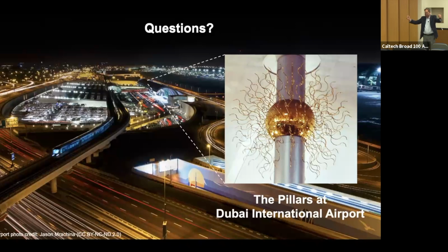the dynamic nature doesn't kill you, right? Because you've locked into a particular site, you've got it tethered down at many different sites, and the breaking and reforming doesn't allow them to tumble. With the tiny particle, where I might only have 4 to 8 oligonucleotides, when one breaks, I can now roll and find another site, and roll and find another site. So the smaller you go, and the fewer oligonucleotide connections you have, the more dynamic the particle is, and you move from what we call a programmable atom to an electron equivalent. My second question is, what about the thermal stability of the crystals that you're making?